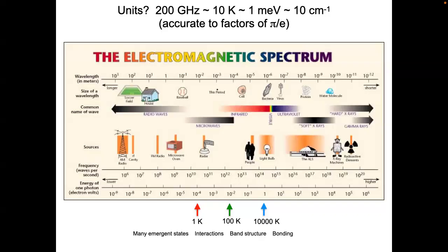One important point that comes out in the study of cooperative phenomena of solids is that if I have some material with interesting physics happening at some particular temperature, very often frequencies on the order of that temperature are an important scale, right? Maybe the canonical example is superconductivity. If I have a superconductor with a transition at, say, 10 Kelvin, where I go from Kelvin to energy with Boltzmann's constant and then to frequency with Planck's constant, those frequencies end up being an important energy scale because that's the binding energy of the Cooper pairs. Okay.